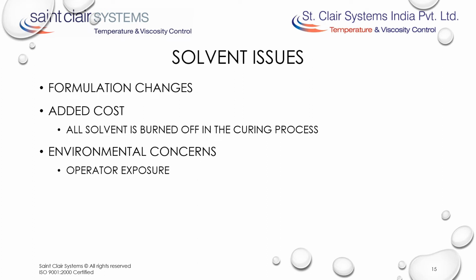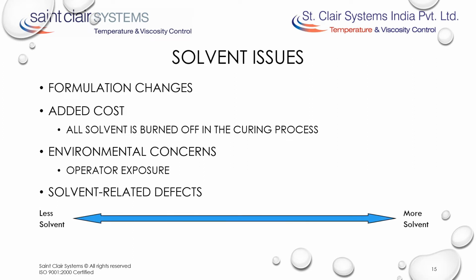To make matters worse, too little or too much solvent can cause defects. We can plot this on a continuum. If we have too little solvent, we get dry spray and all of the associated issues. If we add a little more solvent, we reach the optimal performance level. However, if we continue to add solvent, we start to get cure issues which, as we add more and more solvent, can progress into problems with adhesion, blistering, and even solvent pop. This is why the temperature factor is so important.